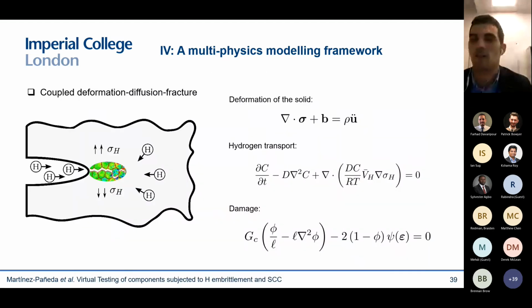So at the end of the day, you have three equations that you're solving. You have one equation for the deformation of the solid, where you normally solve in finite elements, another one for the hydrogen transport, and then the damage. And they are somehow coupled, right? So as you increase the load, you'll have higher strain energy density, so higher probability of cracking, and then higher hydrostatic stresses will also accumulate hydrogen.